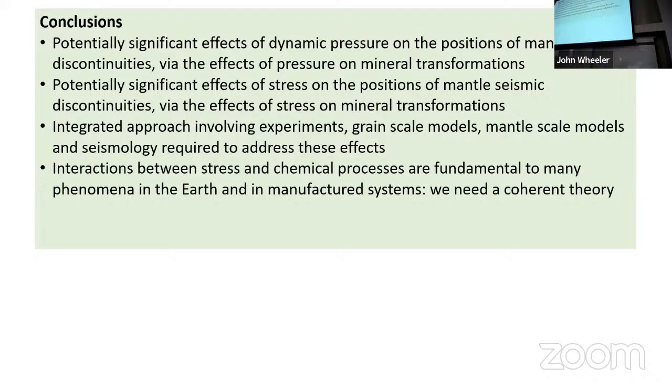So yeah, absolutely. I mean, you know very well how difficult it is, and I agree with you. So Betty's question is, how do we plan to measure the stress in experiments? And part of the answer is, we'll do some of the experiments in a synchrotron. So in the synchrotron, you can use the diffraction patterns of the individual minerals. So stress alters the lattice parameters, and the diffraction patterns allow you to measure the lattice parameters, and so you'll get some estimate of stress from that.